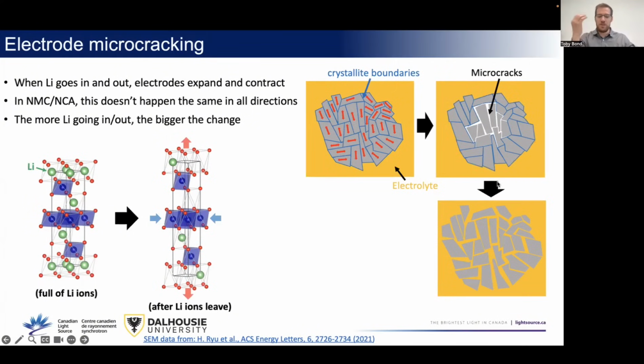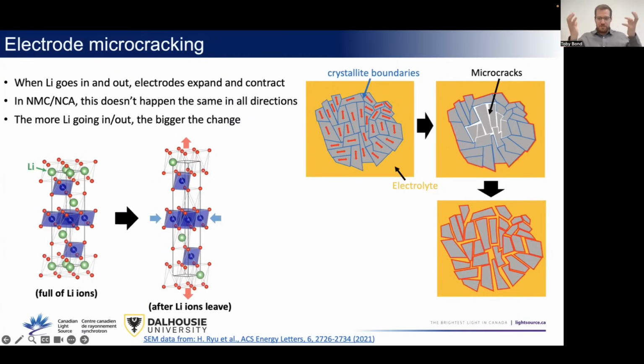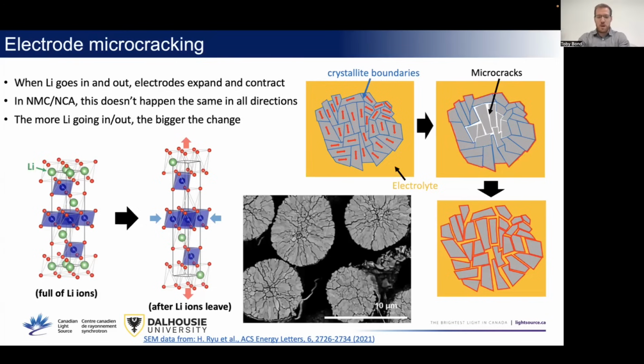Think about all of these reactions I was just talking about. Initially, this red area out here on the boundary of the particle is the electrode surface area that's exposed to the electrolyte. But if the electrolyte is allowed to get inside, then you have all this extra surface area that is now exposed. This increases the rate of those parasitic reactions that we don't want, that remove capacity from the battery. This is what microcracking looks like in an electron microscope image, so I'm not just making this up with diagrams, it's very much real. You can see these little crystal grains, these crystallites, they're a little bit faint, but it's a lot easier to see these cracks that form along the boundaries between them.